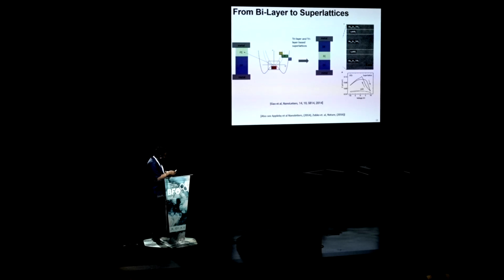So a few years later, we said that it may be advantageous to, rather than doing just one ferroelectric dielectric, let's do a superlattice. And there's no theoretical reason really for it. There is an experimental reason to do it, and let me try to explain that. As just an experimentalist intuition, you want to push the material to where the charge is almost zero in the ferroelectric material, right?